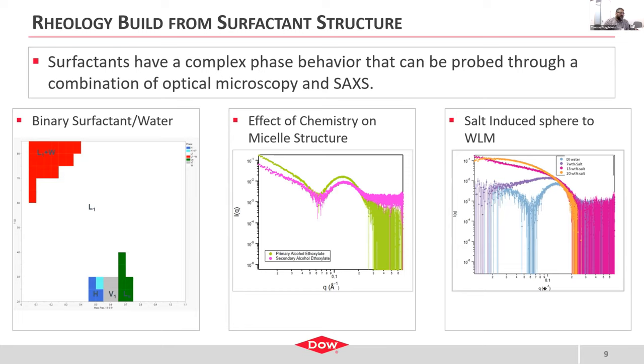These materials often have a complex phase behavior. And what I mean by that is when you put them into water at relatively low concentrations, they're going to self-assemble into micelles. When we look at a binary surfactant phase diagram with water and an alcohol ethoxylate surfactant, shown here on the bottom left, this was measured using polarized light optical microscopy. We can see that from about 0 to about 45 weight percent, it remains optically transparent, no birefringent effects.